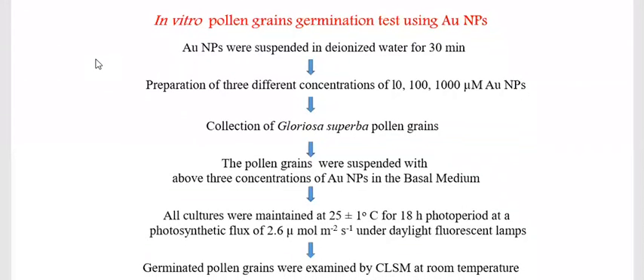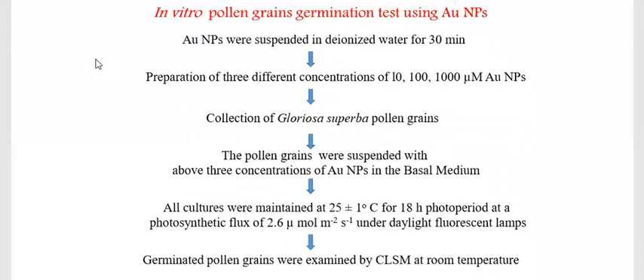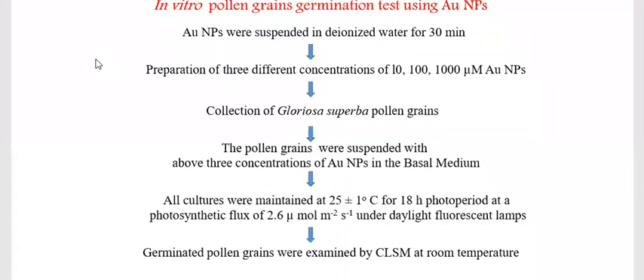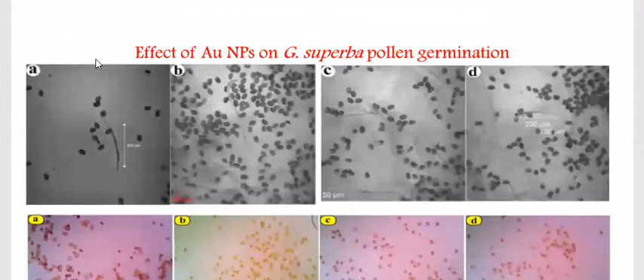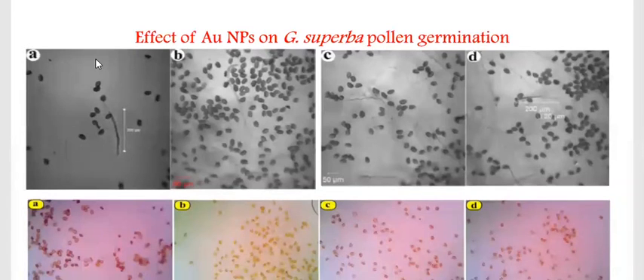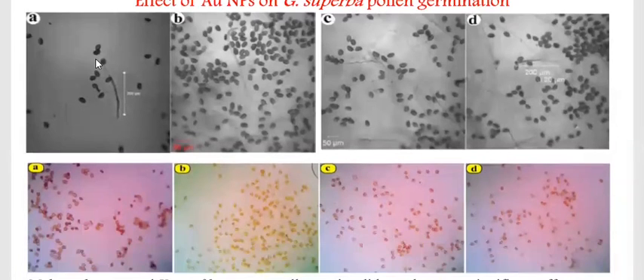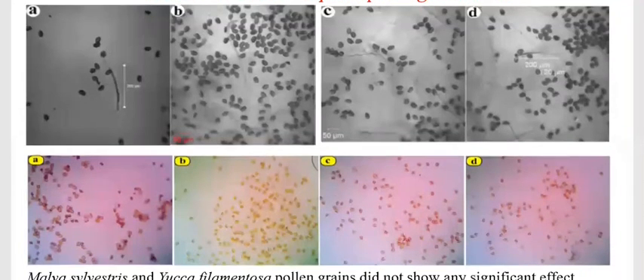So in order, these Gloriosa superba pollen grains were evaluated with gold nanoparticles, using the same protocol used for the basal medium. The confocal image shows A is the control. As the concentration of gold nanoparticle increases, pollen germination increases. It shows a gradual increase of pollen germination activity with gold nanoparticles in 2D, and the normal microscope